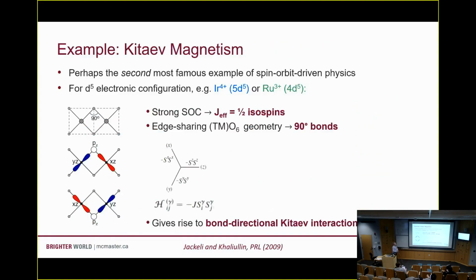So if that's the most famous example of spin-orbit-driven physics, a close second, maybe now the first thing people think about, is not an unusual electronic state, but an unusual magnetic state. One of the things that happens in this strong spin-orbit regime is that your spin and orbital angular momentum are strongly coupled. They become heavily entangled, and so instead of treating these separately, we have to think about them in terms of total effective angular momentum. So for these d5 configurations, you get J-effective 1/2 isospins, and the interactions between these isospins are strongly geometry dependent.